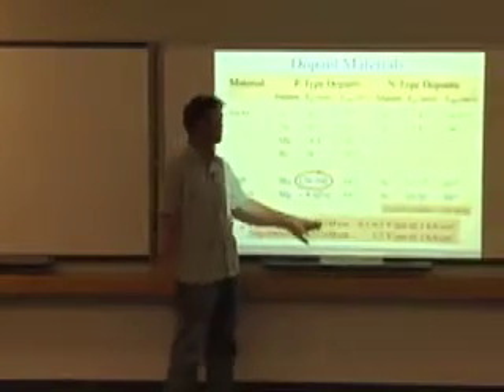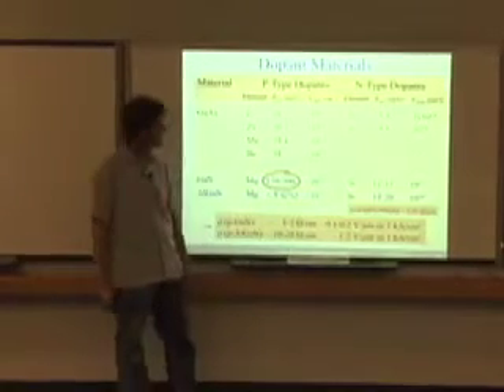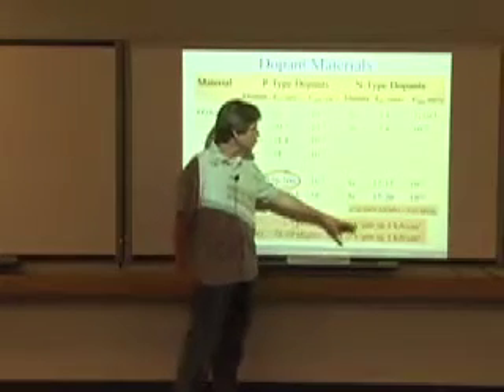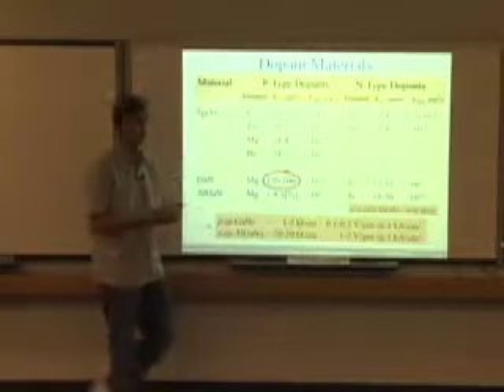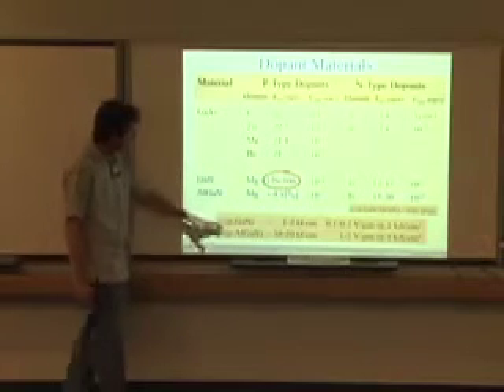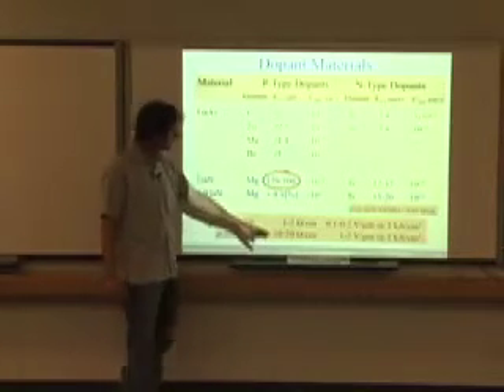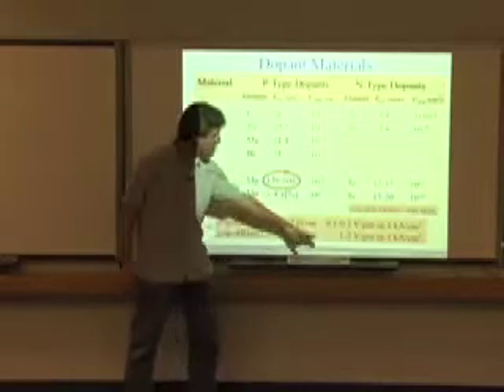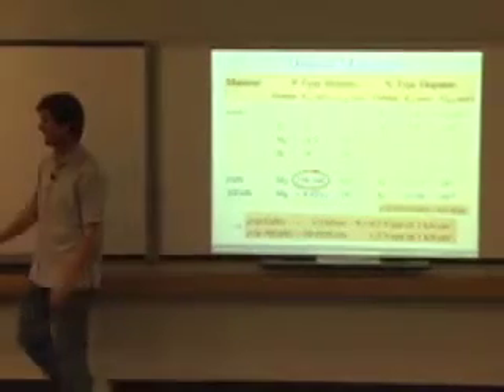And as an example, P gallium nitride would have a resistivity in the range of 1 to 2 ohm centimeters, which translates into just a few tenths of a volt at 1 kiloamp. So for LEDs, this may not be much of a problem. But if you go to AlGaN, you're looking at a factor of 10 higher than that. And so 1 to 2 volts at 1 kiloamp. You can have as much as that.